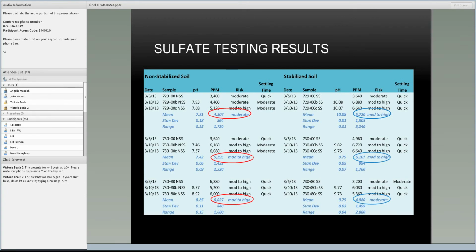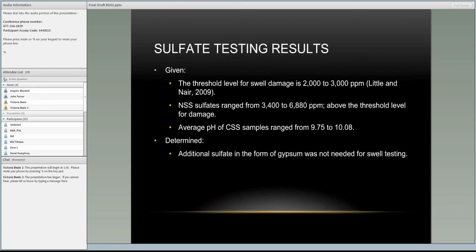So after doing the sulfate testing, given that the threshold level for sulfate for SWELL damage is 2,000 to 3,000 parts per million, and given the high sulfate readings for the non-stabilized soil above 3,000 parts per million, and that the pHs were getting pretty high on the cement stabilized soil, we determined for creating our SWELL samples that additional sulfate in the form of gypsum wasn't needed. We felt pretty confident that swelling could happen and ettringite growth could happen without the addition of any sulfates.